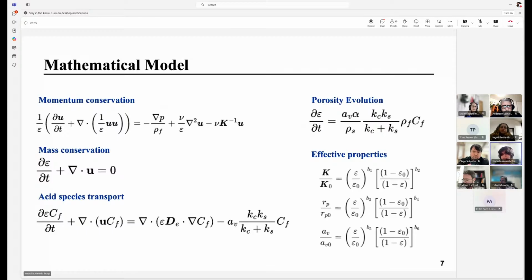Here's a brief look at the mathematical model that's being used. We have momentum and mass conservation to solve for velocity and pressure, the transport of the acid species, a porosity evolution equation, and some equations that relate to permeability, pore radius, and interfacial area, and how they will change as the porosity changes due to dissolution.